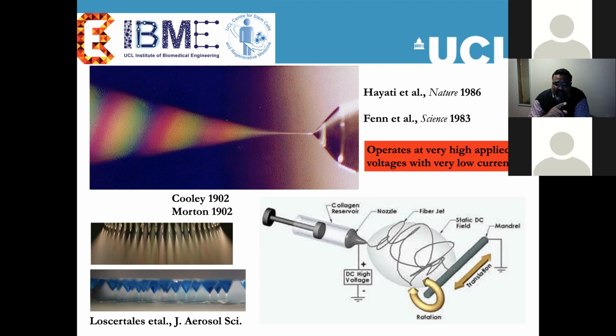Unlike in 3D printing, where the jet is double the size or more than the needle, in electrosprays and in electrospinning, the actual jet that emanates is maybe 1/100th the size of the inner bore diameter. Therefore, resolution is not a problem.